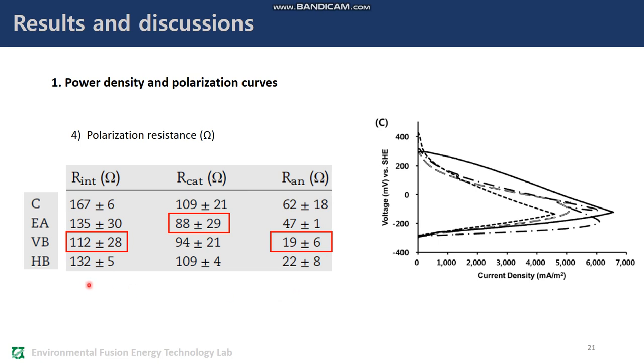Polarization resistances for a full cell were 167 ohms for C, 135 ohms for EA, 112 ohms for VB, and 132 ohms for HB, showing the brush anode cells had slightly smaller values. Cathode polarization resistance ranged from 88 to 109 ohms. Full cell polarization resistance was correlated with the anodic polarization resistance.